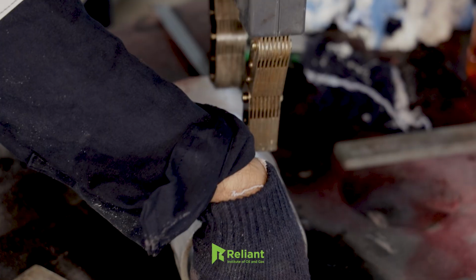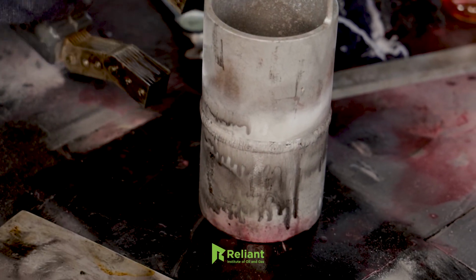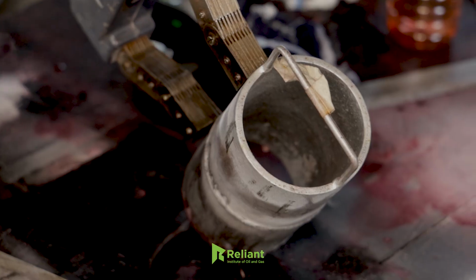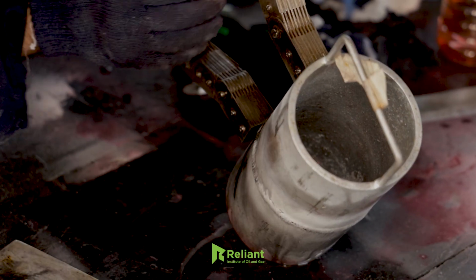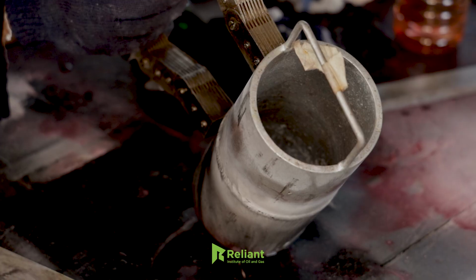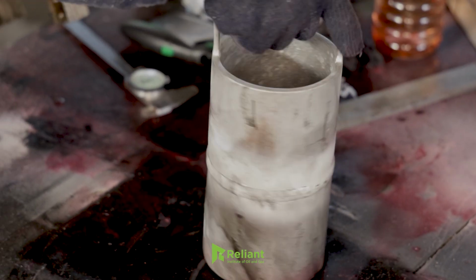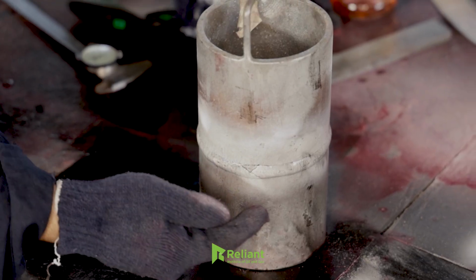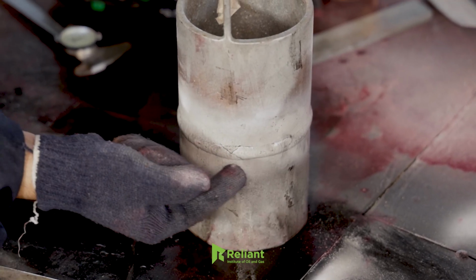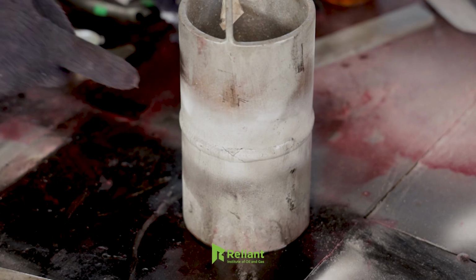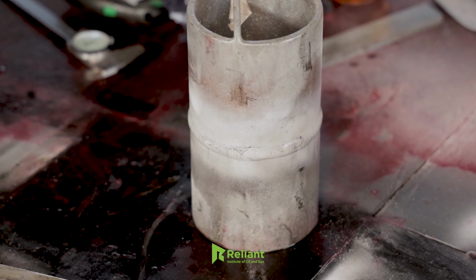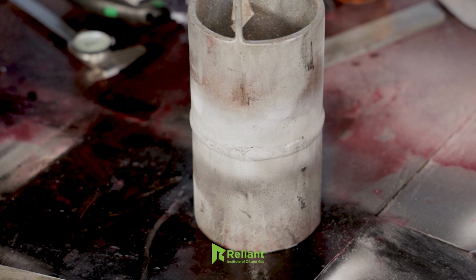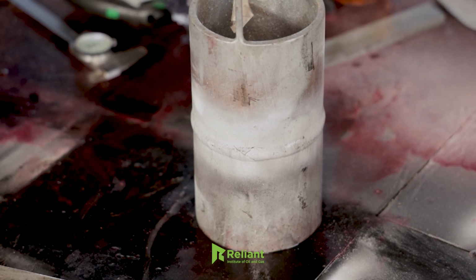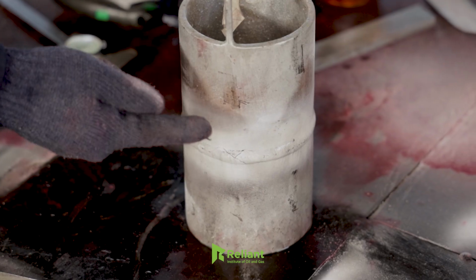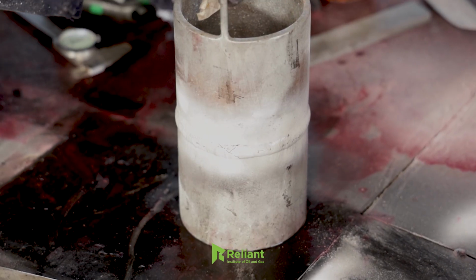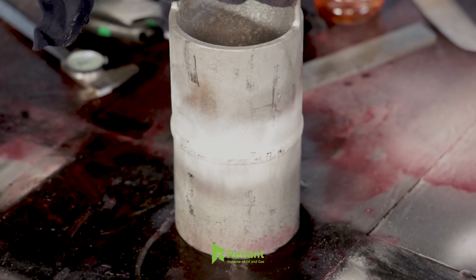Yep. So here we have a better indication. Yes. So you can see here a branched crack from here and from here, and from the bottom it is connecting. Just see the beautiful indications we got. So before, 2 cracks we found in the bottom plate and the top plate, then now we can see a branched crack in between the 2 plates, and we are going to check some more further.